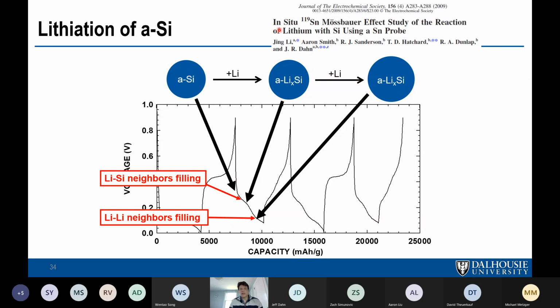And a nice paper by Jeff used Mossbauer spectroscopy. They doped silicon with some tin to figure out what the bonding environment was around the host atoms. And this first single phase region was associated with lithium bonding with the silicon phase, so you're forming lithium silicon bonds. But then eventually you run out of silicon that is able to bond with lithium. And so the lithium is forced to go in places where it only has lithium neighbors. And that occurs at much lower potential. It's more difficult to do. And that's why you get this second plateau.